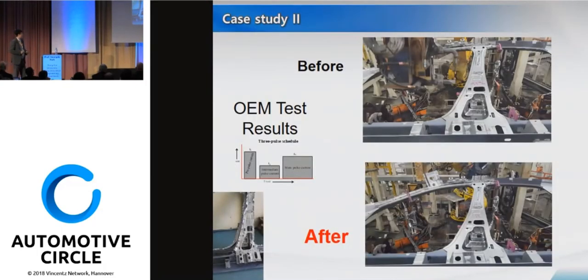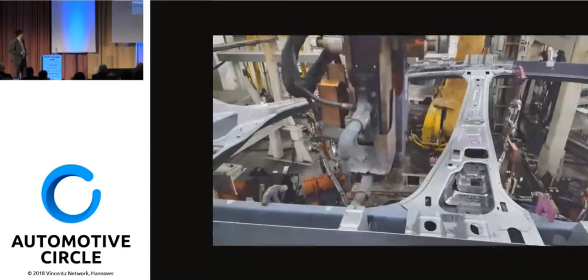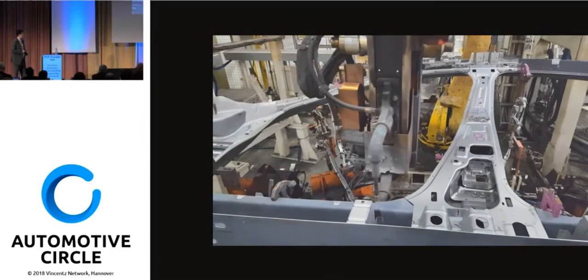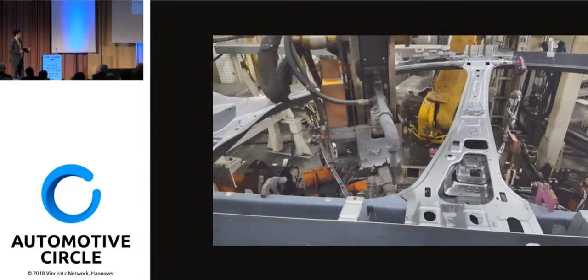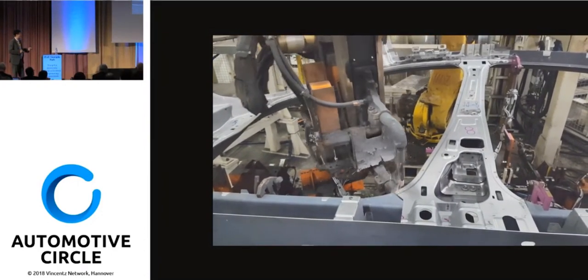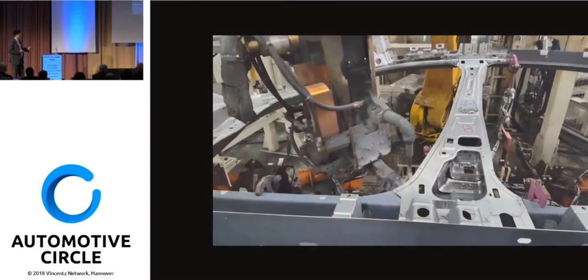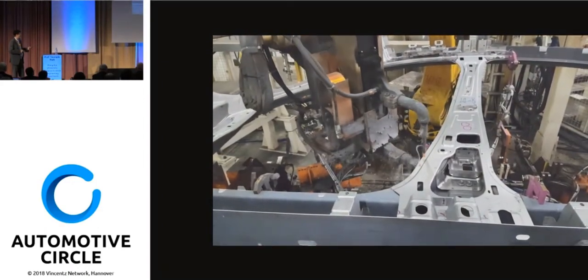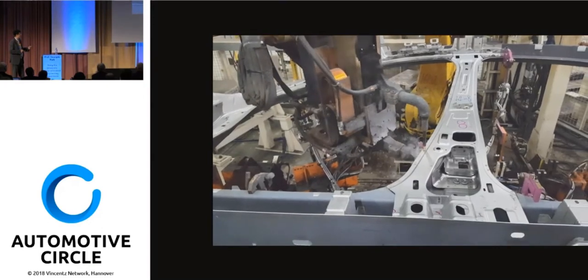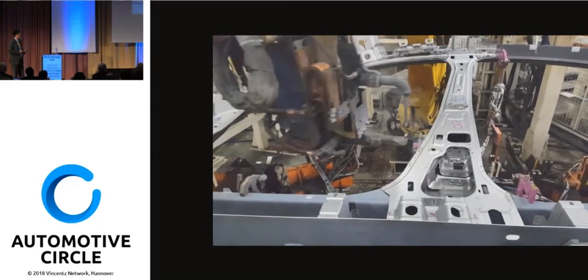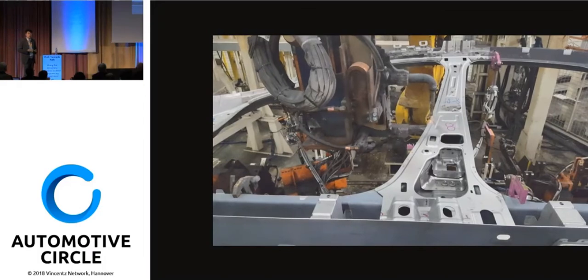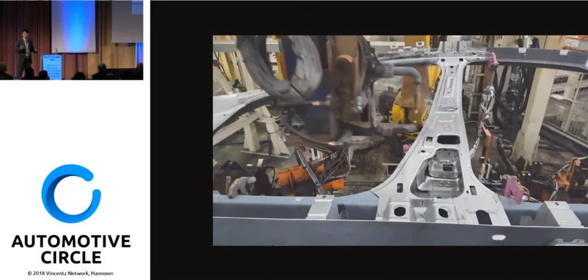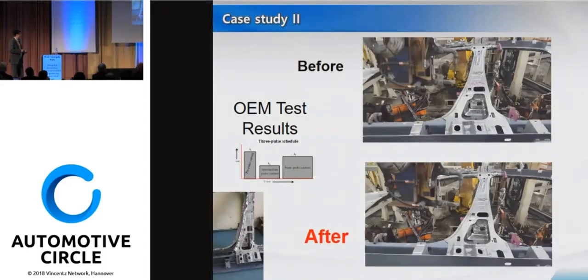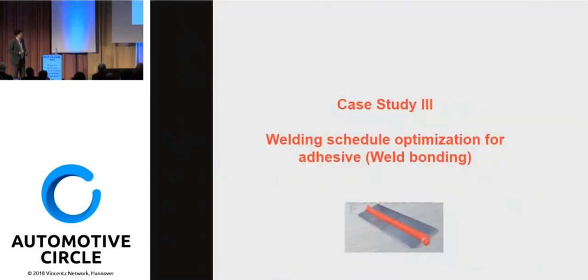And we provided them our optimum welding condition, first the current profile, and this is what we got. Not much spatter here, but you can see some smoke. One spatter was here, but otherwise no spatter, just a lot of smoke. So I think the manufacturing line was almost spatter-free. Then they checked the destructive test. It was all button failure, so it was very successful.